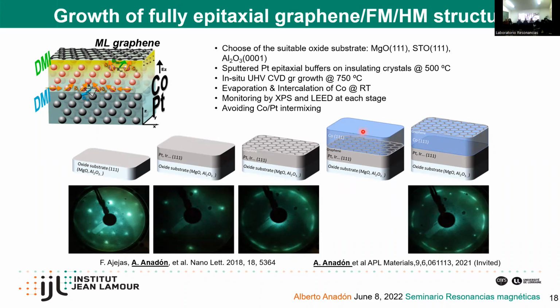And then what we do is we heat this sample, and the cobalt tends to travel on the surface of graphene and goes beneath graphene. When cobalt does this, it becomes an epitaxial layer just below graphene. So what we have in the end is a sample on an oxide substrate in which we have a completely epitaxial stack that we will use later. I will show you now the characterization for this.